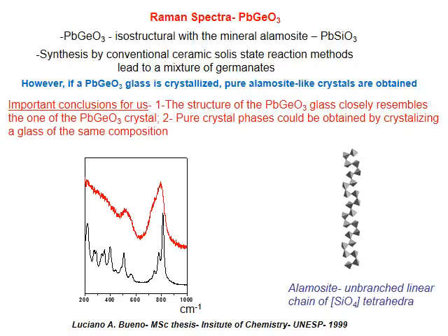By classic, I mean mixing lead oxide and germanium oxide precursors, long comminution in a mortar, pressing in pellets, and long heat treatments at temperatures given by phase diagrams, where the only stable phase was this lead germanate. Even with heat treatments of some days, he always obtained a mixture of different lead germanates with different formula.